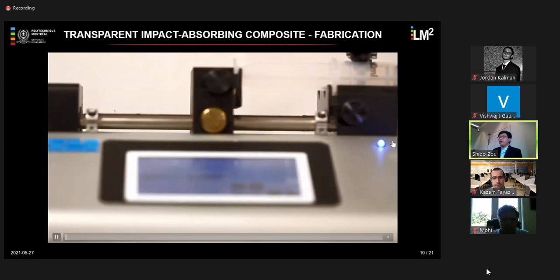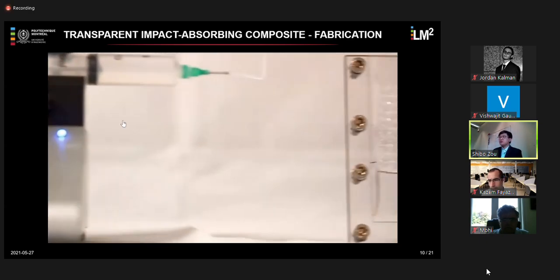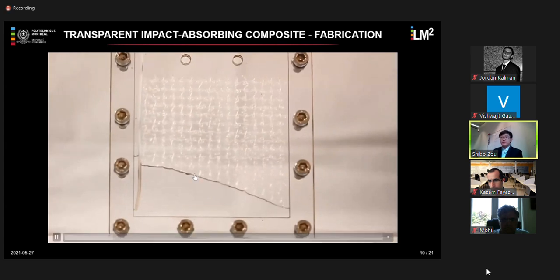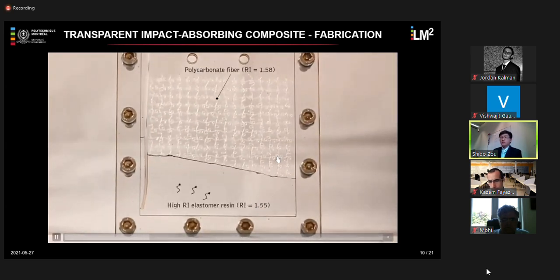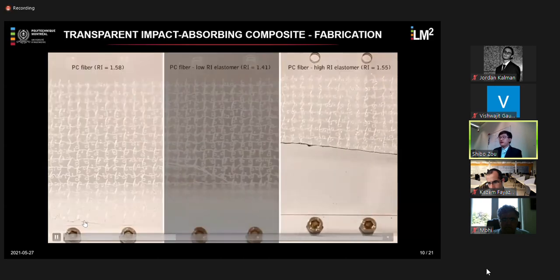And later, we developed a resin injection system using a syringe pump to inject a transparent elastomer resin around this fiber fabric. And in this project, we used two different elastomers. The refractive index of our fiber fabric, the polycarbonate fiber fabric, is around 1.58. And we use two elastomers with different refractive index. One is much lower than the PC fiber, which is around 1.41. And the second one is a high RI elastomer with a higher refractive index, which is around 1.55. This one is much closer to the PC fiber.